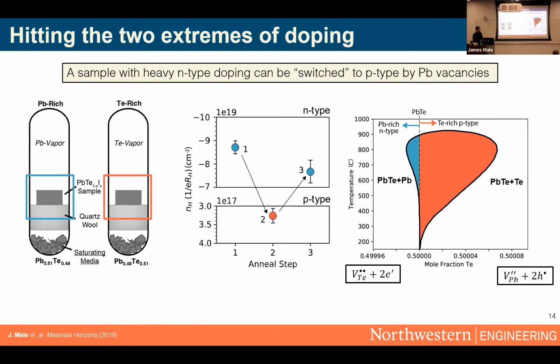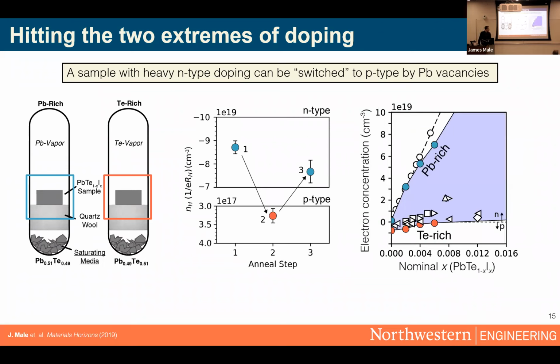If I take that same sample and make it tellurium rich, I actually get a P-type sample. So I've added an N-type dopant, but by making the sample tellurium rich, I've added so many lead vacancies that you don't even get the right conduction type. If I take the same exact thing and anneal it lead rich again, I actually recover most of that carrier concentration. So I can reliably flip my composition back and forth across a phase width. What that means in terms of doping efficiency is I'm getting near perfect doping efficiency in my lead-rich samples, but abysmal doping efficiency in my tellurium-rich samples. So you can start to see where the inconsistencies arise.